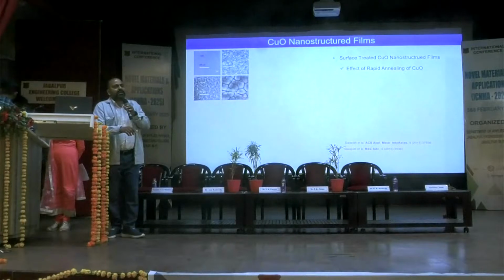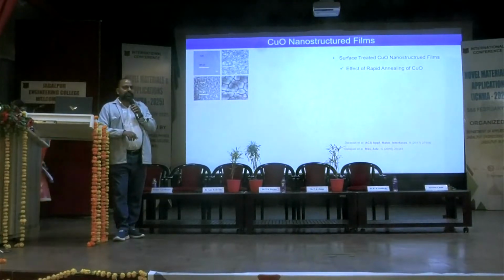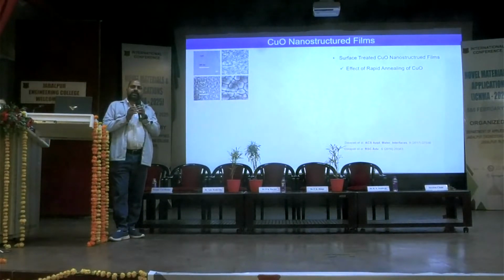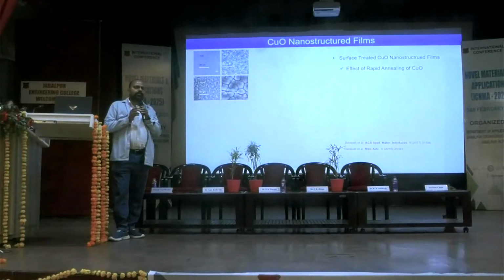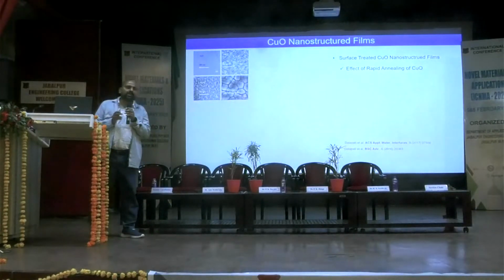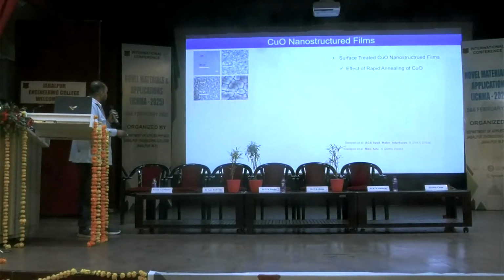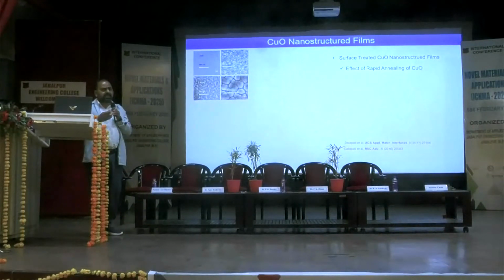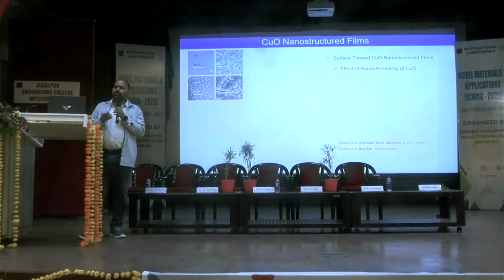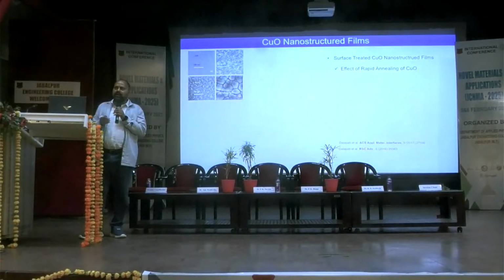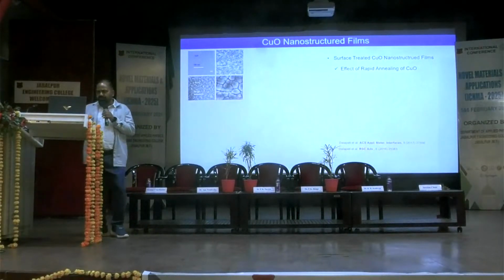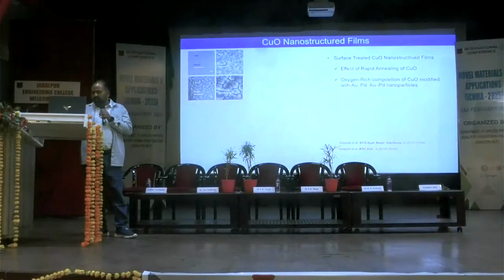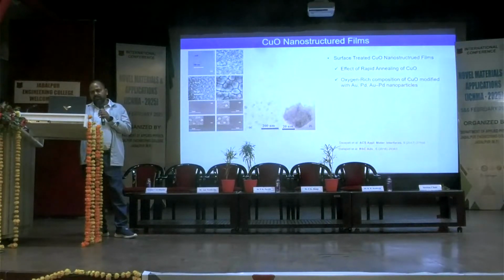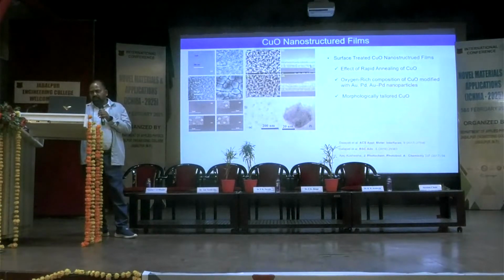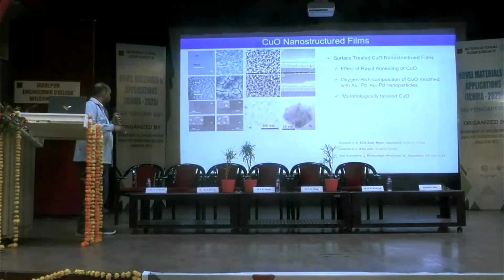So see, we worked earlier on two different sets of materials. One was zinc oxide, the second was tin oxide. Then we thought, why not look toward P-type materials which have a lower band gap, and we started with the copper oxide system. Again we utilized a sputtering based setup, with a solution process also. We developed different types of nanostructures on the surface of copper oxide, basically on FTO and also on silicon. Again, we published this work in different journals.